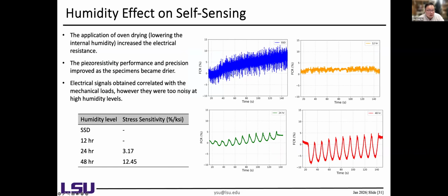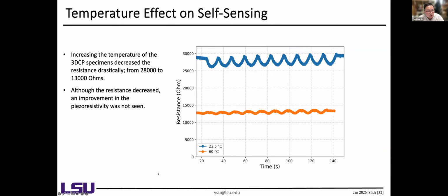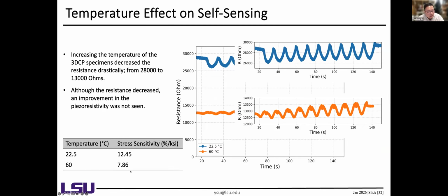So we further convert that, from the previous slide, that is the resistivity, to the FCR, and then calculate the stress sensitivity. Apparently the 24 hours and the 48 hours, specifically 48 hours, give us the better sensitivity. And for temperature, we tested 2 different temperatures for the pilot study, 22.5 degrees, which is the normal temperature, and 60 degrees. We observe that if we increase the temperature, the self-sensing performance actually decreases. And here shows you the stress sensitivity.